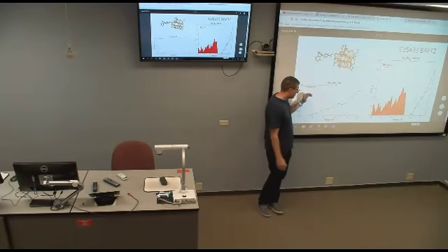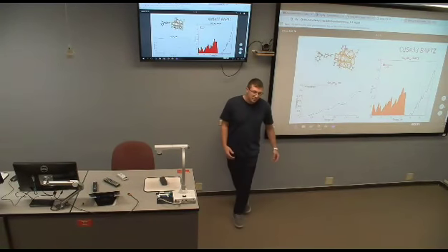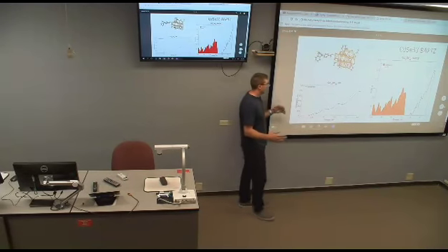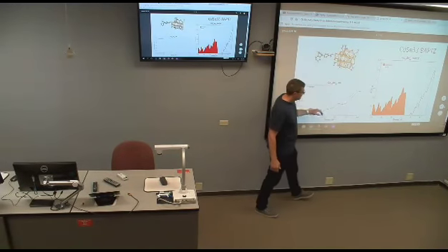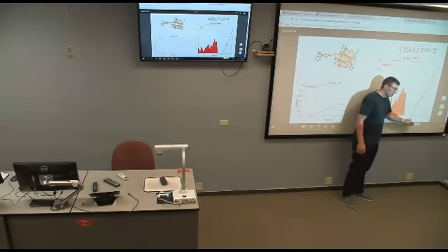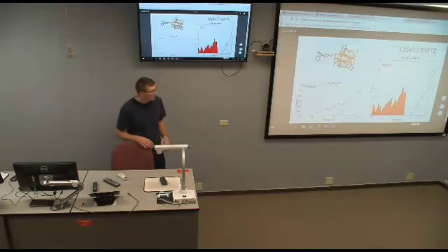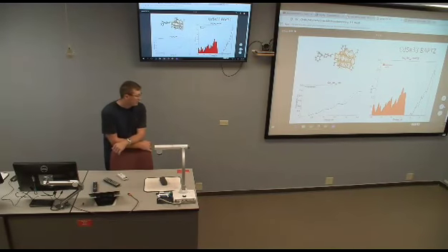So their absorption spectra start closer to this 2.8 at this peak here, whereas the absorption spectra for these models now has primary absorptions close to this band gap value, so it's going to be greatly redshifted compared to what the experimental values are.